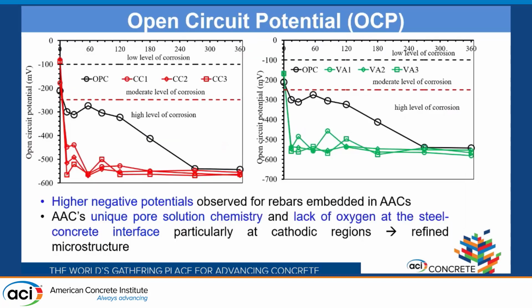So let's see what our results are. These are the trends for open circuit potential. We note that CCs and VA based alkali-activated concrete rebars show a very high level of corrosion since the beginning of the experiment itself. But this is with respect to the OPC limits. You see there is a drop in the beginning itself and then it stabilizes in the same region. However, the OPC, the black line, the OPC specimens, degrade over time. The level of corrosion is high as per the code here as well.